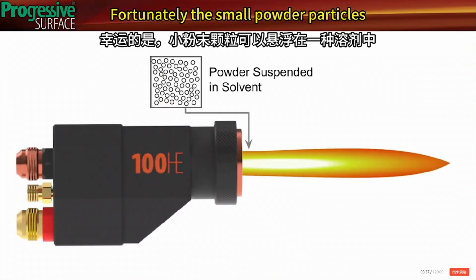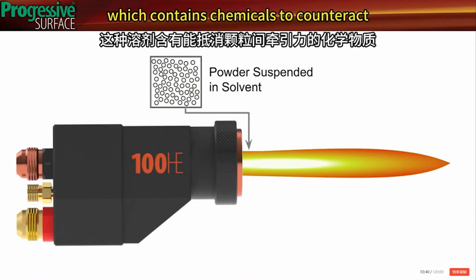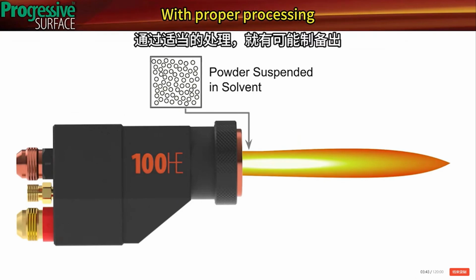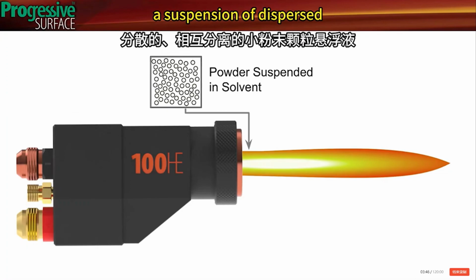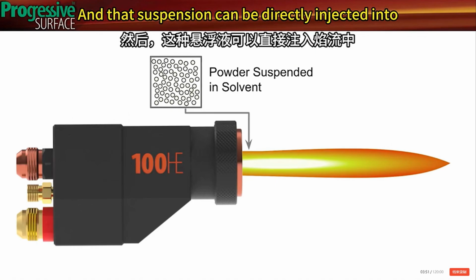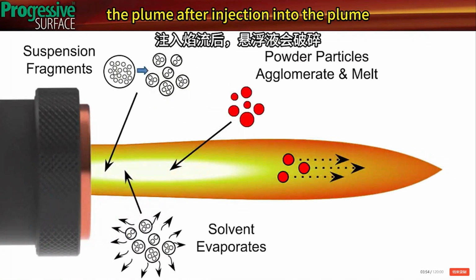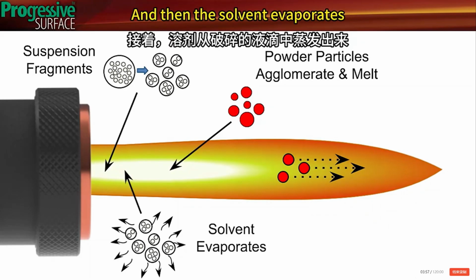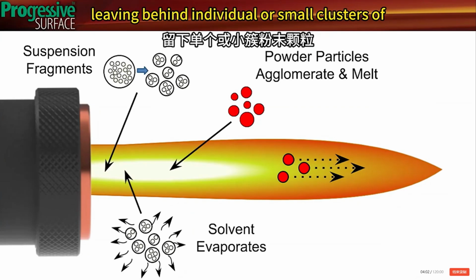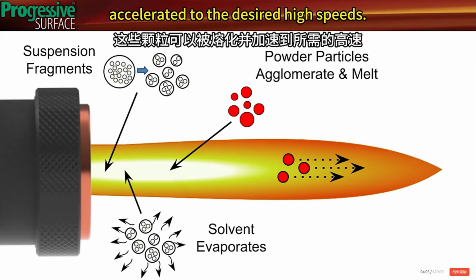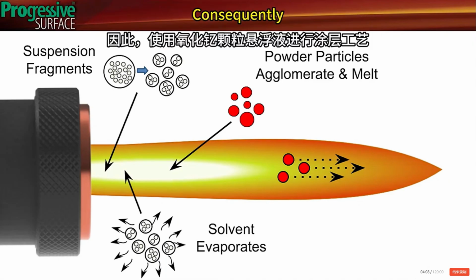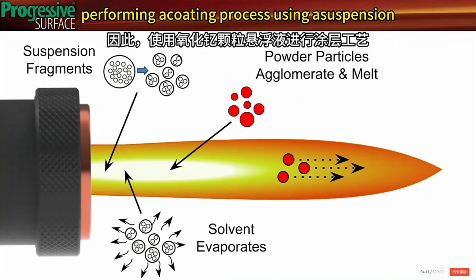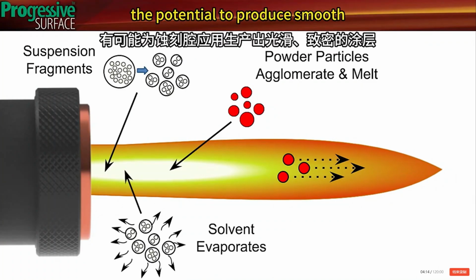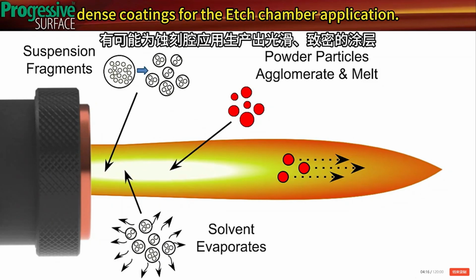Fortunately, the small powder particles can be suspended in a solvent which contains chemicals to counteract the interparticle attractions. With proper processing, it is then possible to produce a suspension of dispersed, separated, small powder particles, and that suspension can be directly injected into the plume. After injection into the plume, the suspension fragments, and then the solvent evaporates out of the fragmented droplets, leaving behind individual or small clusters of powder particles that can be melted and accelerated to the desired high speeds. Consequently, performing a coating process using a suspension of yttrium oxide particles has the potential to produce smooth, dense coatings for the etch chamber application.